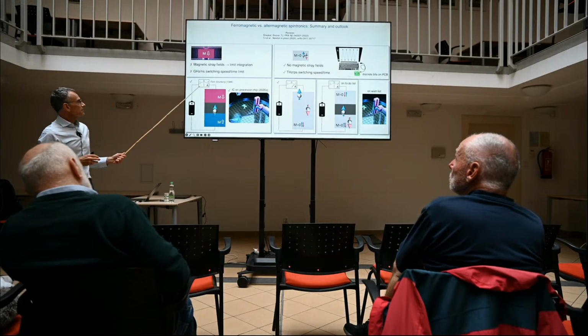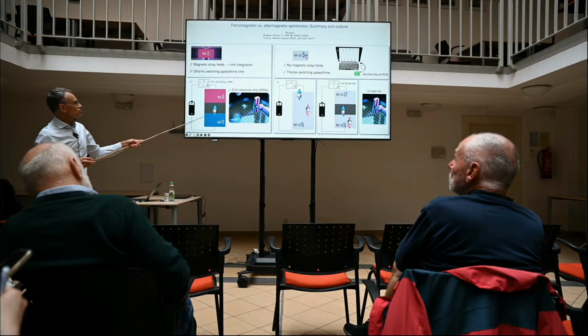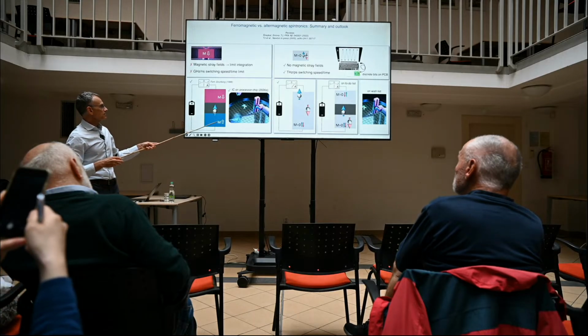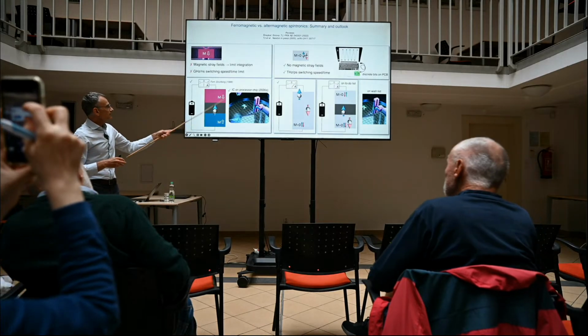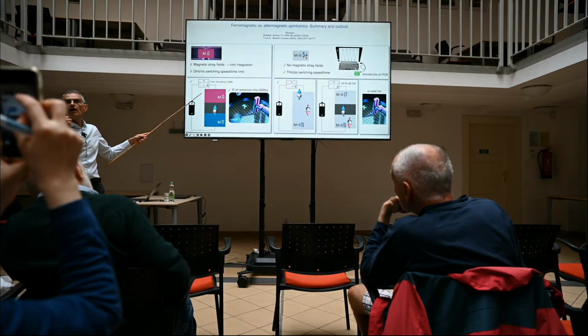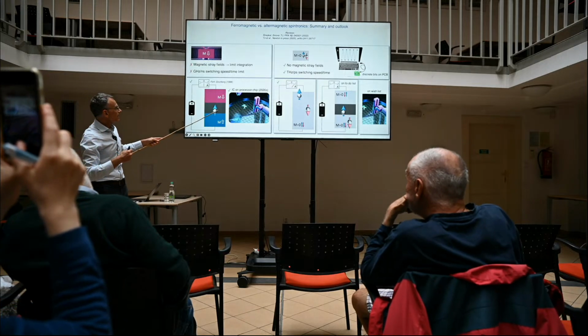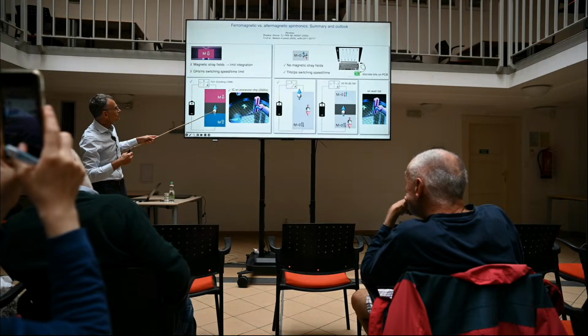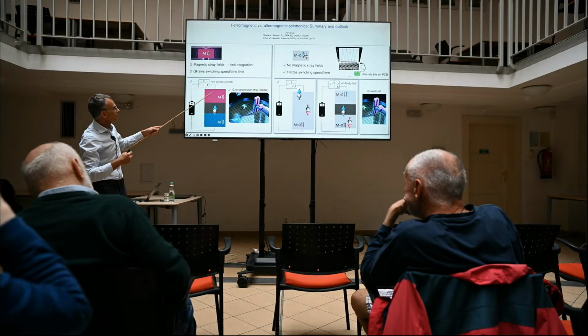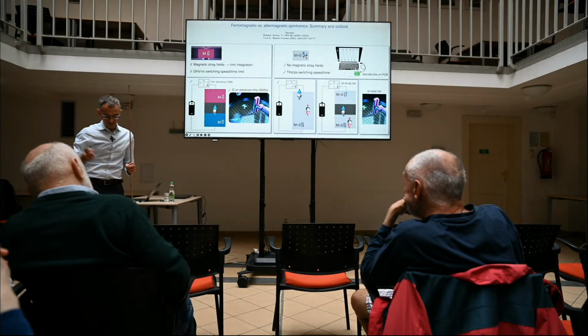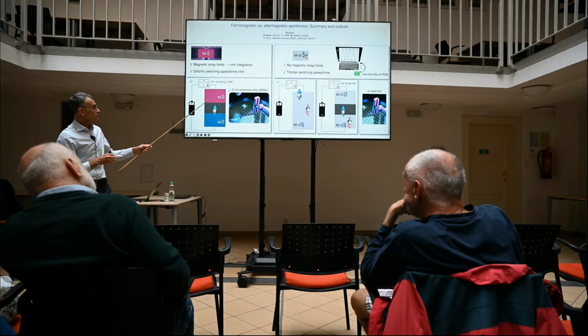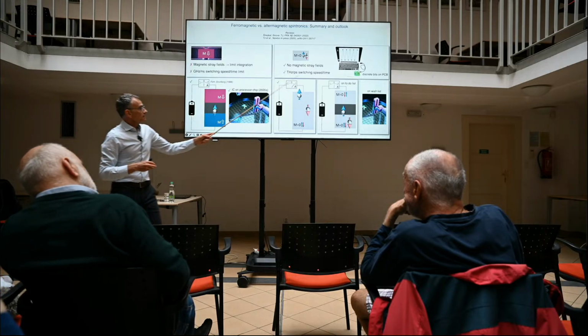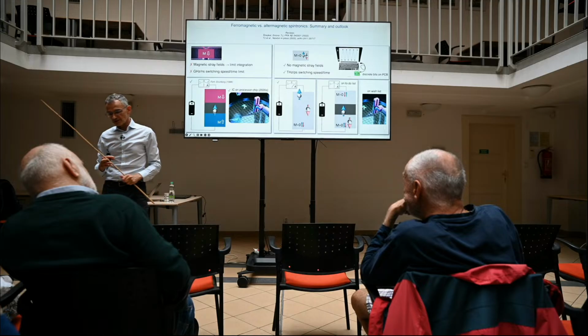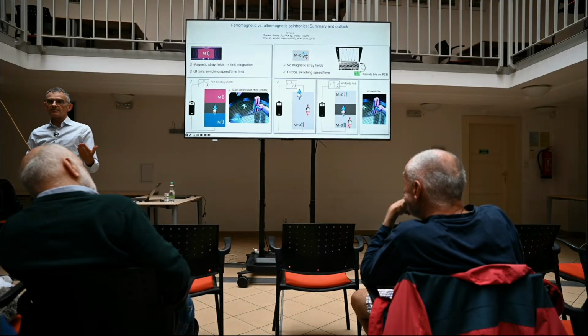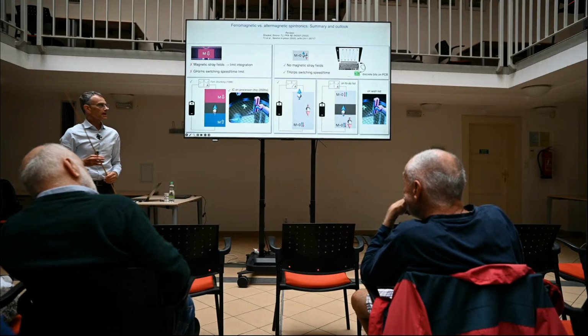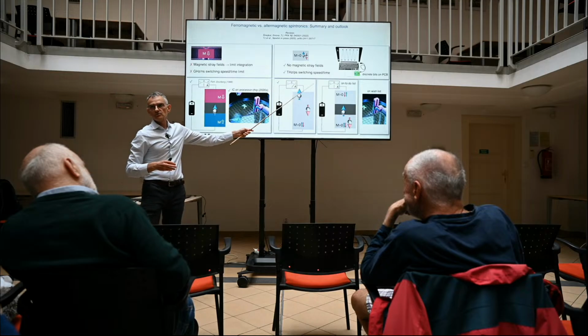But the critical thing in ferromagnetic spintronics was not just that we have spin polarized current in one magnetic electrode, but that we can build this so-called spin valve device, that we can have this multilayer stack in which we can block the electrical current depending on the orientations of the spins on the two respective electrodes. This is something which has been theoretically predicted to work equally well in altermagnets, but on the experimental side, this is still on the to-do list.